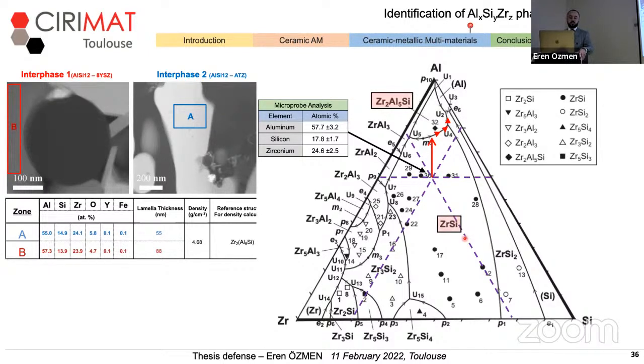And while cooling, the composition might be going through, as shown with the red arrow, and it can meet the ternary phase area, which was accepted as a reference point. And due to fast cooling or quenching, it can be locked in this composition. So kinetically as well, the appearance of this ternary phase and the intermetallic phase is possible.